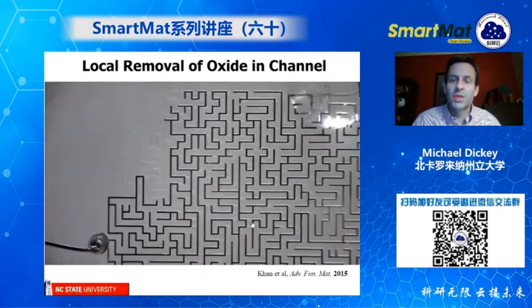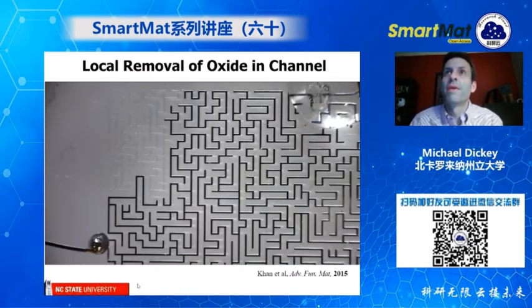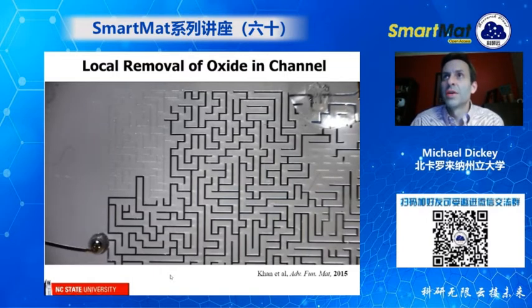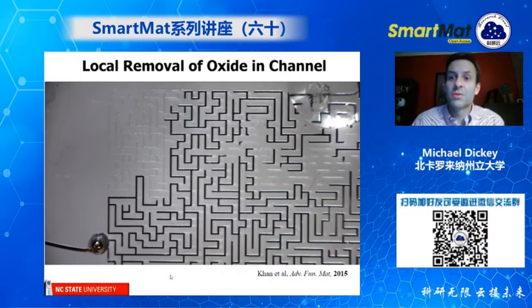So we showed that you can actually do this in a microchannel. Let me pause this for 1 second and explain what you're looking at. These dark lines are the liquid metal. Over here, there's a reservoir of liquid metal, and there's an electrode that we connect to it. Over here is a reservoir of water, and we connect an electrode to it, and we apply a voltage. When we apply the voltage, you'll see that it removes the oxide layer, and it causes the metal to withdraw from the microchannel.